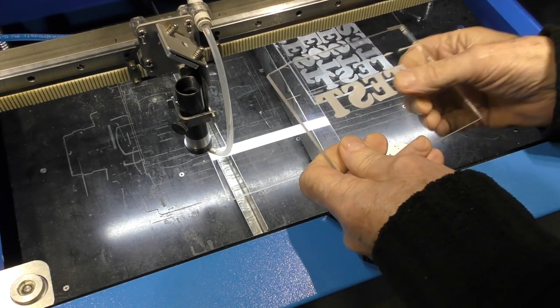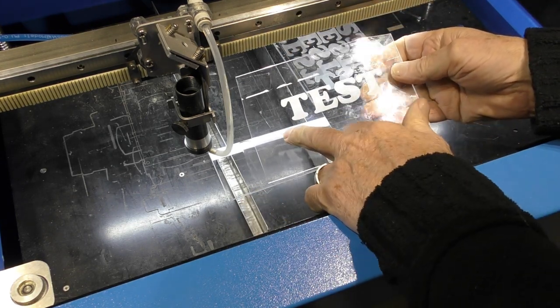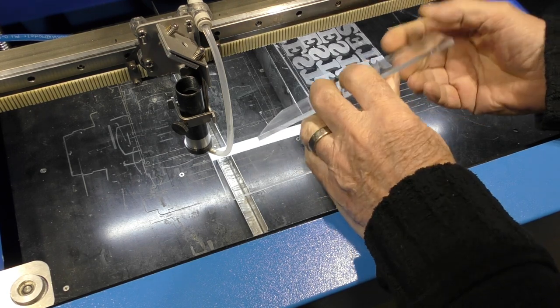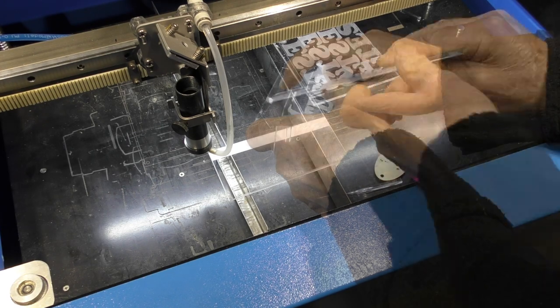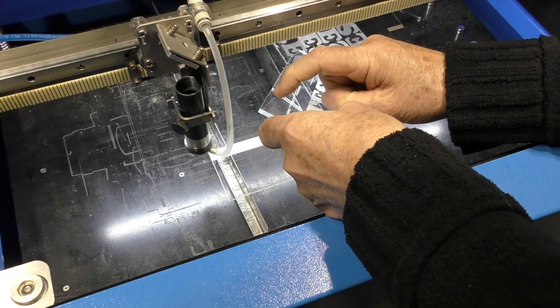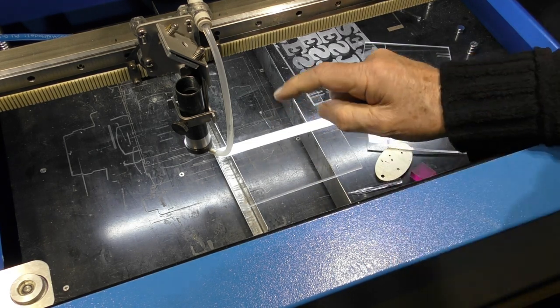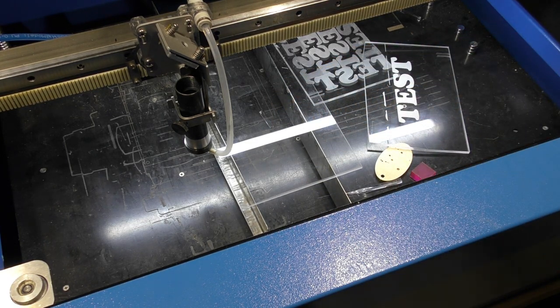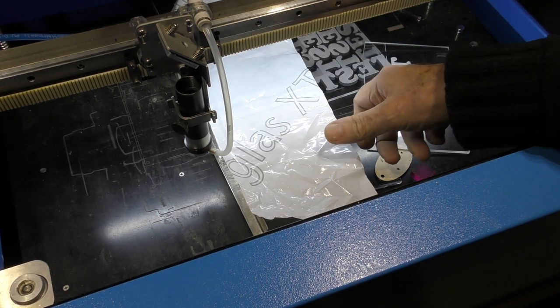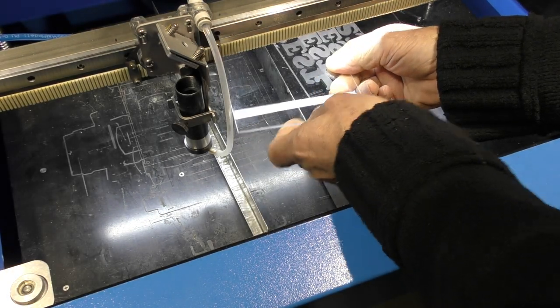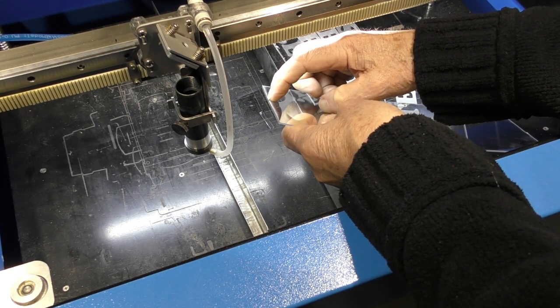Right well here's my first test on cast acrylic. And I know this is cast acrylic because I've got all the striations along here from the cutting. When I put my fingernail over the edge there there's no hint of a burr. This on the other hand is definitely extruded acrylic. How do I know that? There's a piece of protective film that came off of it. XT. When I cut the end off this one you can hear my fingernail clicking over the burr.